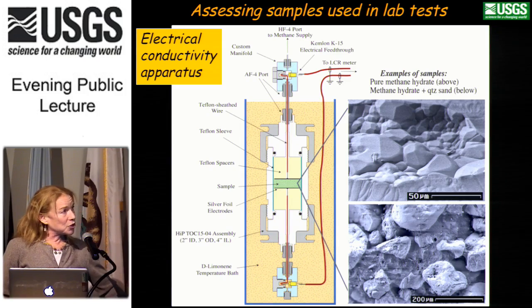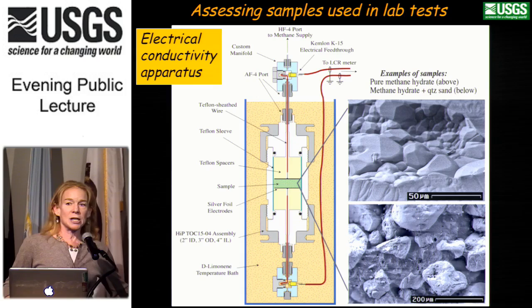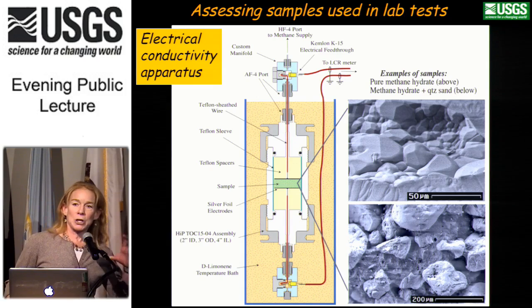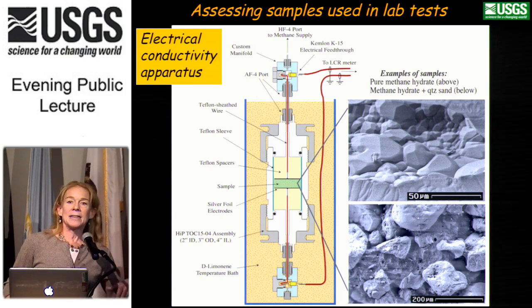The upper photo to the right shows methane hydrate at about 50 micron scale, and the bottom picture is methane hydrate plus a quartz sand mixture. So in the tests that we do here, usually we start first of all with a pure end member methane hydrate, and then we'll add in components one at a time to understand the effects on the properties.